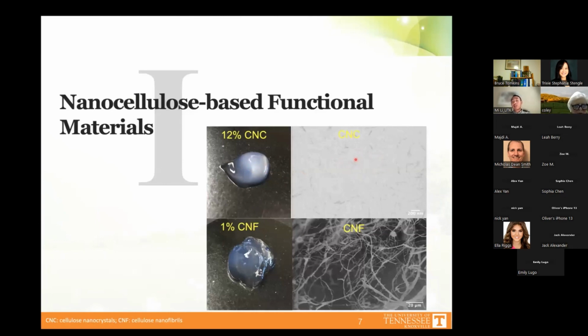And this is how the CNC looks under the microscope. It's hard to see, but this is a 200 nanometer scale. So it's about 200 to 300 nanometers in length and about 20 nanometers in width. And this is a 1% cellulose nanofibril. It really looks like a gel, both of them look like gels, okay?